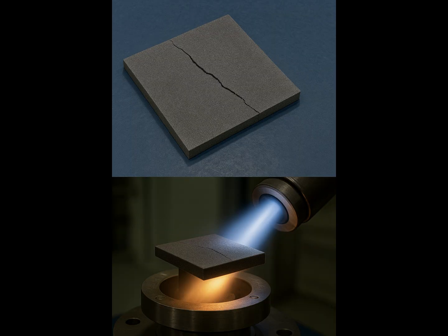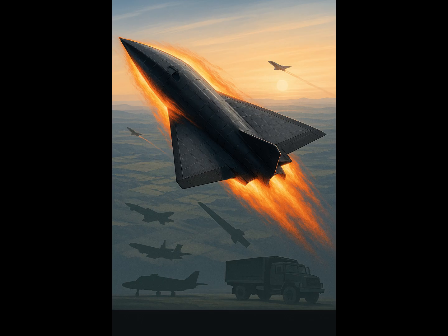DARPA milestones: what we deliver. 1. Six-month demo. Validate self-healing at greater than 1,500 Celsius with greater than or equal to 70% flexural strength recovery after cracking. Materials will also undergo thermal cycling to simulate flight damage, confirming durability and repeatability of the healing mechanism under hypersonic conditions. 2. Flight-relevant thermal protection system component.